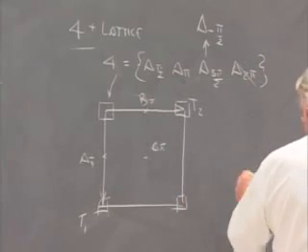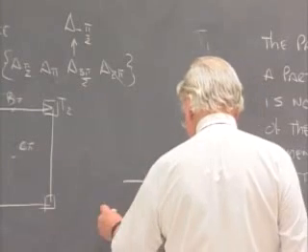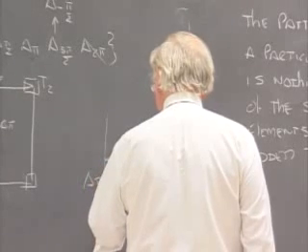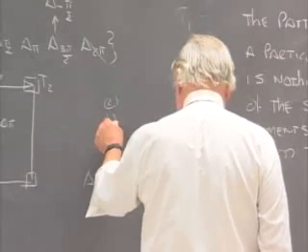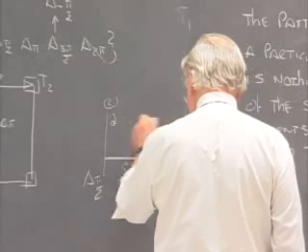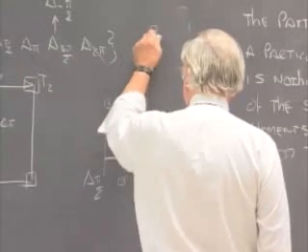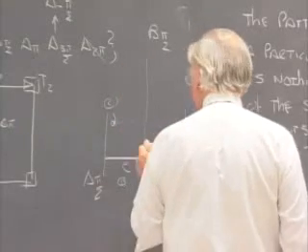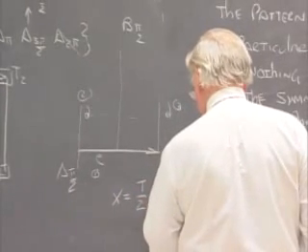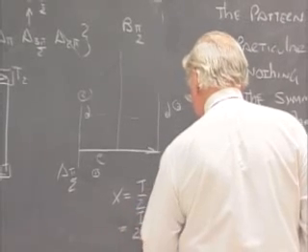So the one that's really different is the combination of a translation, T, with the operation A pi over 2. And my theorem says if I put in a motif and rotate it by 90 degrees to here, so this is number 1, and this is number 2, and then translate it to a location that's related to the first by symmetry, by translation, to get number 3, they will be related by an operation B pi over 2 that sits up along the perpendicular bisector by an amount x, which is t over 2 times the cotangent of alpha over 2,